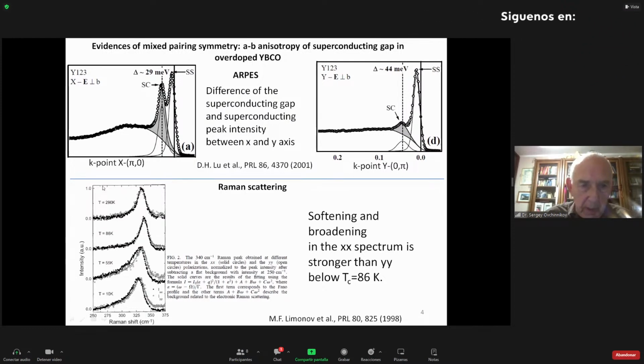Also in Raman scattering, it was found that softening and broadening of the spectra are different in the x direction and y direction for strongly overdoped samples.